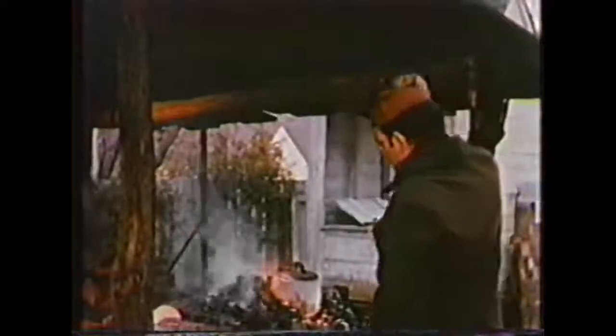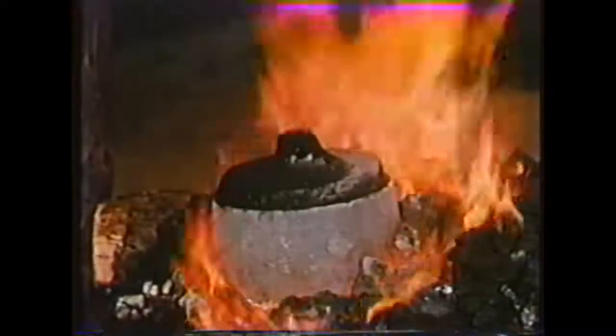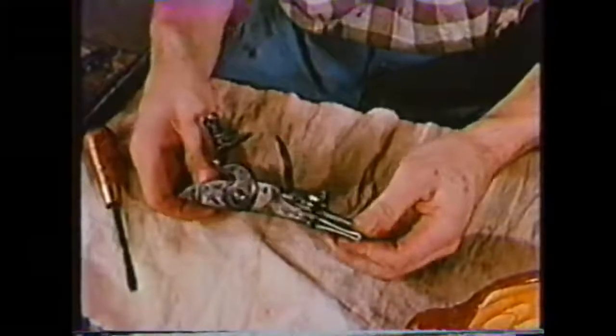Sealed from the air and surrounded by this mixture, they'll be heated red hot in the forge. The surface of the iron will absorb carbon and thus be converted to steel, while the body itself retains the resiliency of wrought iron. After 5 or 6 hours of heating, the surface steel is hardened by quenching in water. The finished lock is put together and tested for spark.